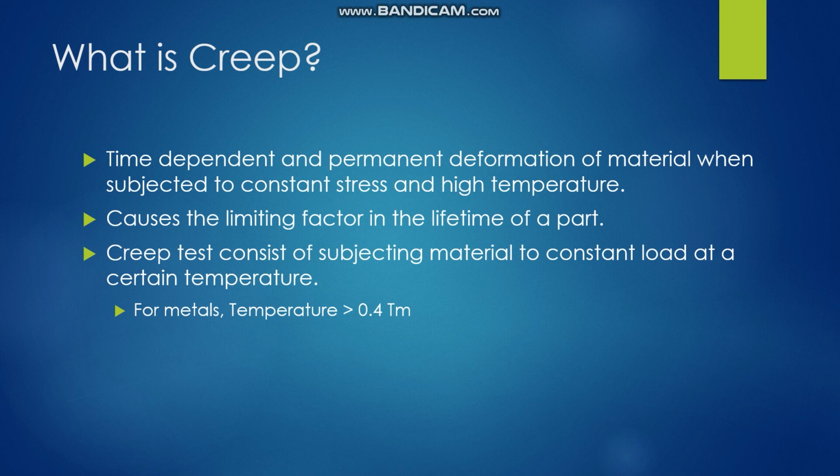Creep is almost like fatigue in a way, but in this case, temperature and constant load is the main cause of failure. It is defined as the time-dependent and permanent deformation of material when it's subjected to constant stress and high temperature. Creep itself most often causes the limiting factor of lifetime of a material, especially when it's exposed to high temperature. We can see this in applications such as turbine and power plant. It is also important to note that generally, the temperature needed for creep to happen is above 0.4 absolute temperature of melting point.